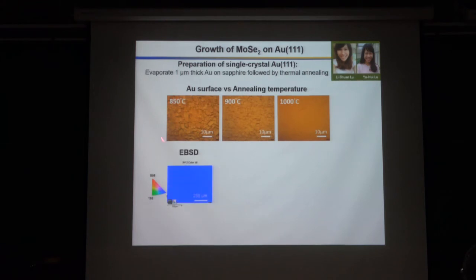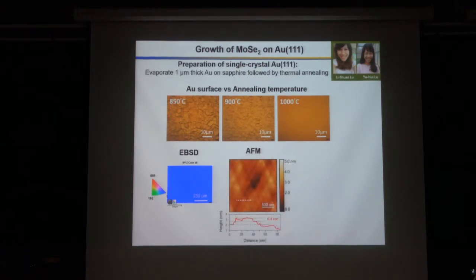So this is electron backscattering diffraction. You can clearly see this direction is, I'm sorry, this is 111. So this is the 111 direction. And also we use atomic force microscopy. The surface shows very clear atomic steps. So this is a very clean gold 111 surface.